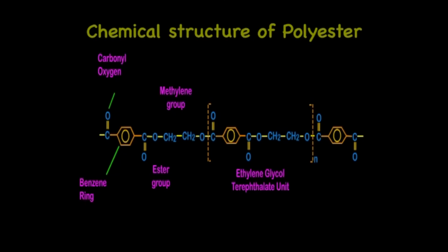Even though there are not many hydrogen bonds present, because of the low polarity of the carbonyl oxygen and also the hydrogen, which does not have much polarity, it is difficult to form hydrogen bonds. But there are a number of attractions because there are a number of electrons present below and above the benzene ring, and these form very attractive bonds, and thus polyester fiber is very stable for many chemical reactions and also for normal usage.